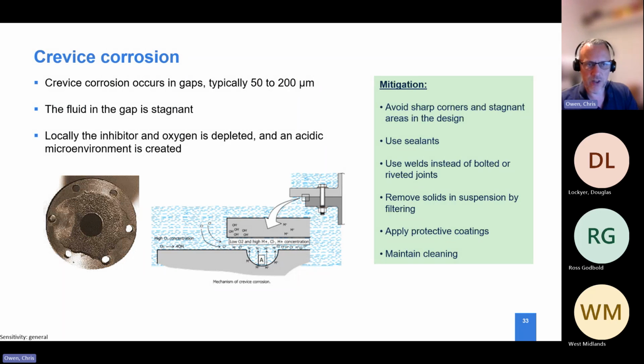Other types of corrosion which initiate, we call crevice corrosion. Now, crevice corrosion is normally associated when you've got two different components next to each other, either a flange plate or a bracket or something like that. However, crevice corrosion also occurs within pipework systems, particularly if the internal weld bead has not been trimmed properly. You end up with a sort of internal lip where the oxygen at that point is depleted, so it's more prone to corrosion. And again, there's issues which we're aware of, and again, mitigation which can be put in place. And we'll talk about crevice corrosion again a little bit later on in one of the examples we show.